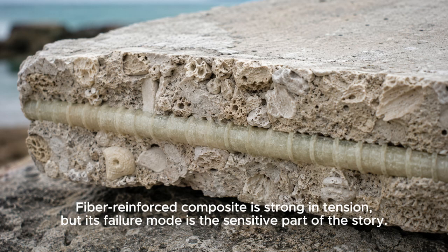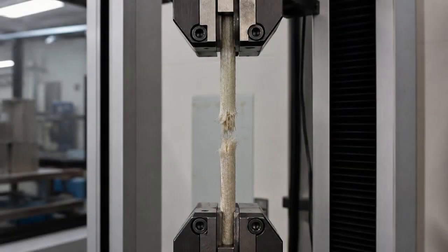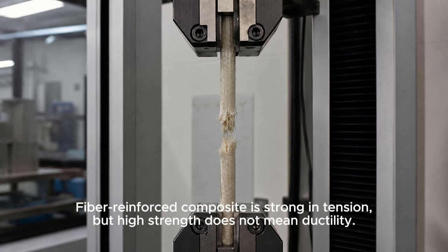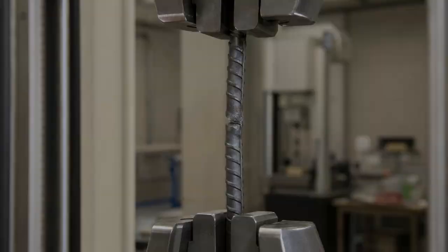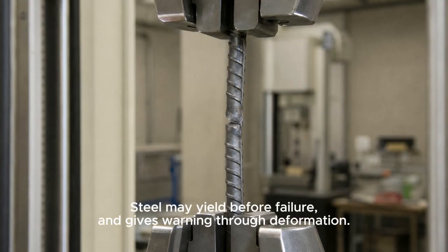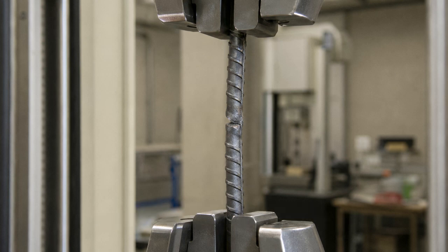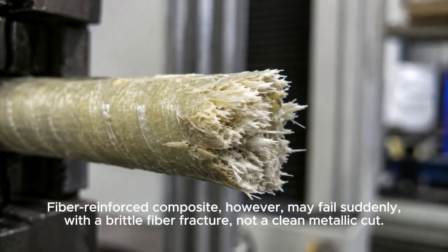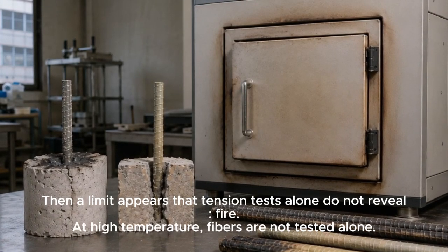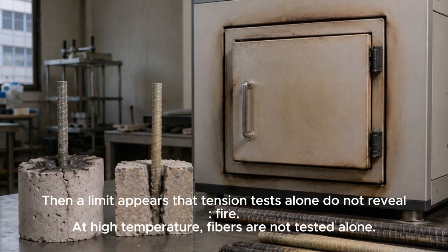Fiber-reinforced composite is strong in tension, but its failure mode is the sensitive part of the story. High strength does not mean ductility. Steel may yield before failure and gives warning through deformation. Fiber-reinforced composite, however, may fail suddenly, with a brittle fiber fracture, not a clean metallic cut. Then a limit appears that tension tests alone do not reveal: fire.